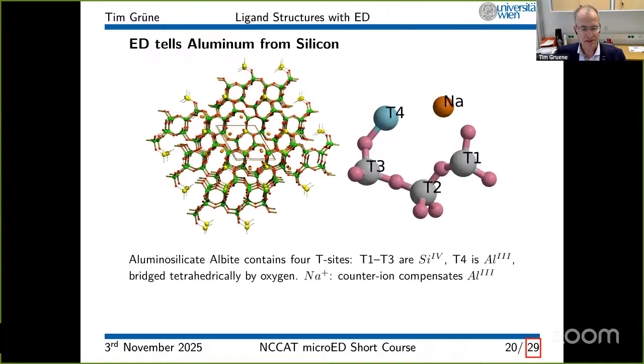This is a very technical example, but I would like to show you the differences in terms of R value based on this. This is a benchmarking sample that we have. It's an albite, an aluminosilicate. So this is the asymmetric unit. We have 4 T sites and they're coordinated by 4 oxygen atoms each. The T sites are mostly silicon. So the gray ones are silicon, and one of these T sites is aluminum.